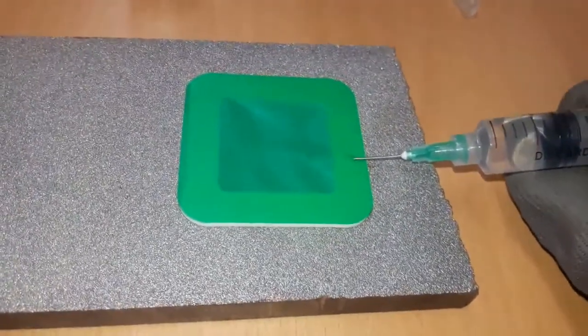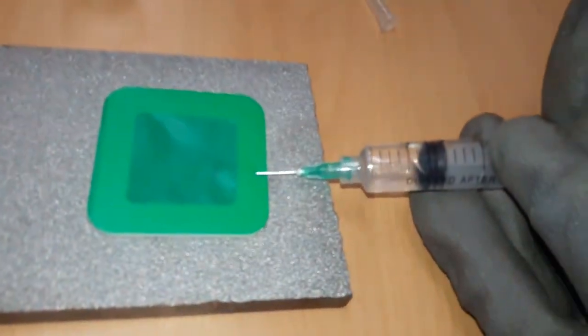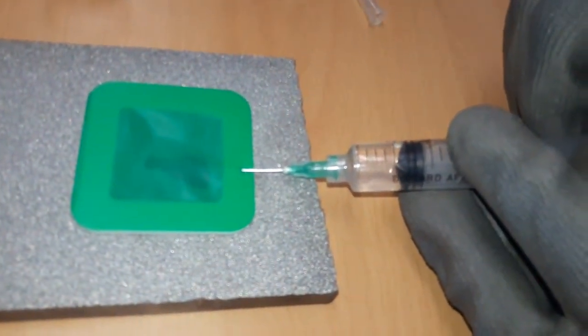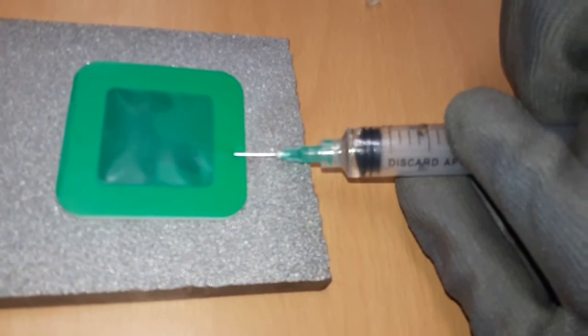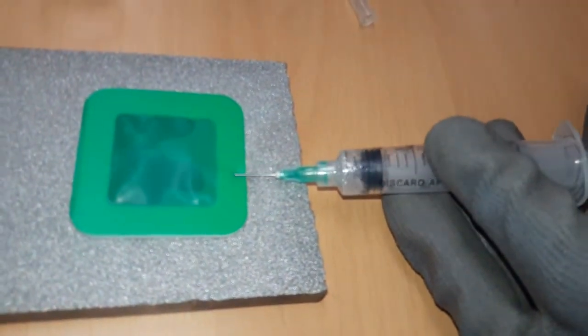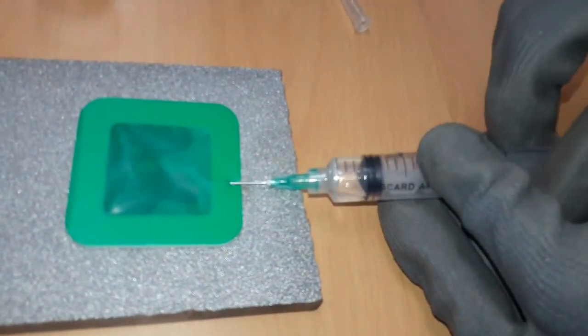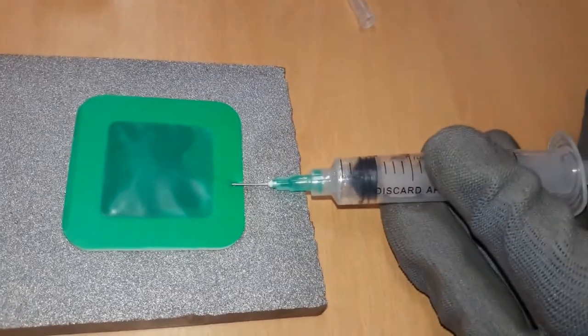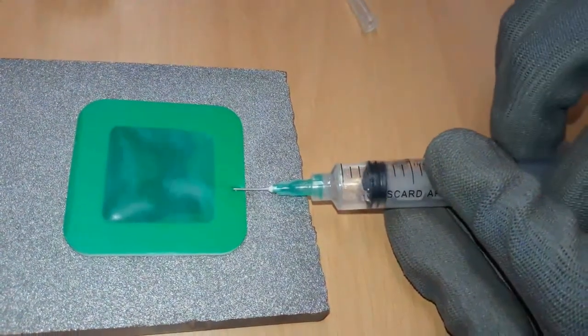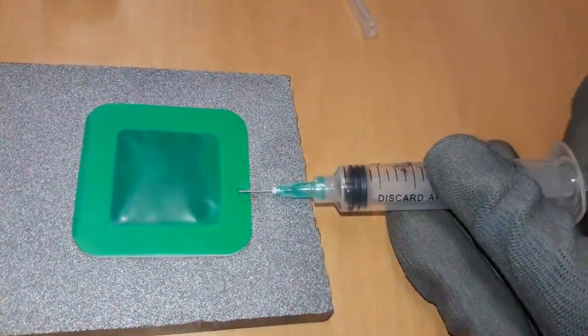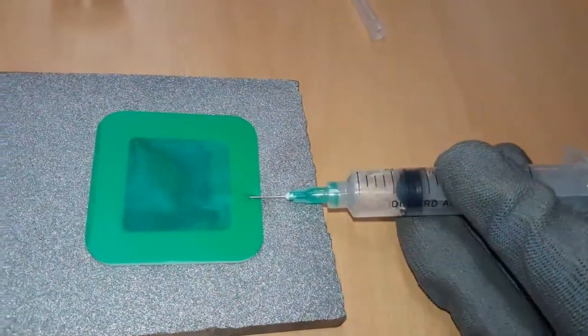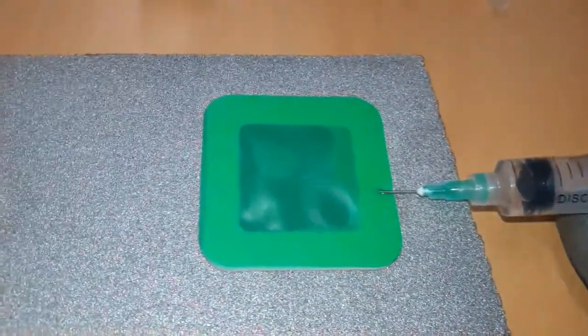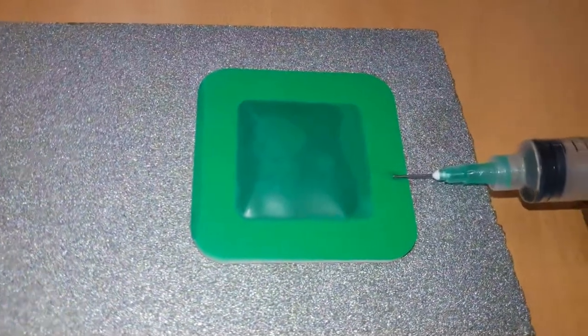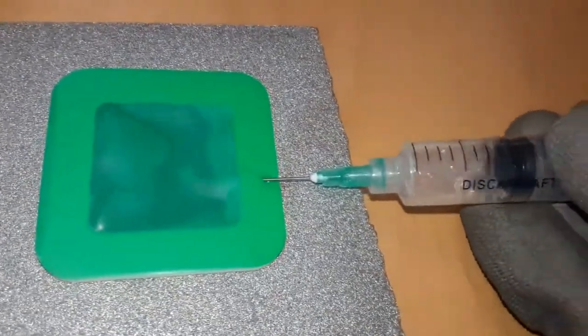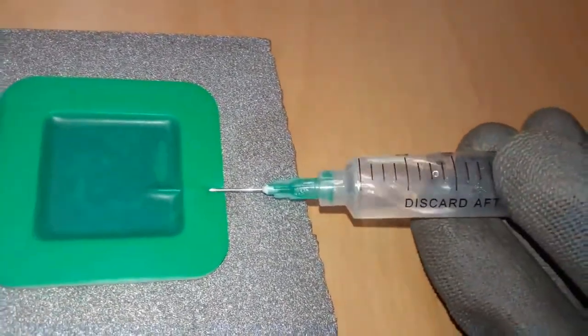Without removing the syringe needle from the patch, re-inject the solvent into the compartment and then suck the solvent back into the syringe cylinder. Repeat until at least 4 injection-sucking cycles have been completed. At the end of the last cycle, retrieve as much as possible of the solvent from the compartment and transfer it to the 25 ml beaker.